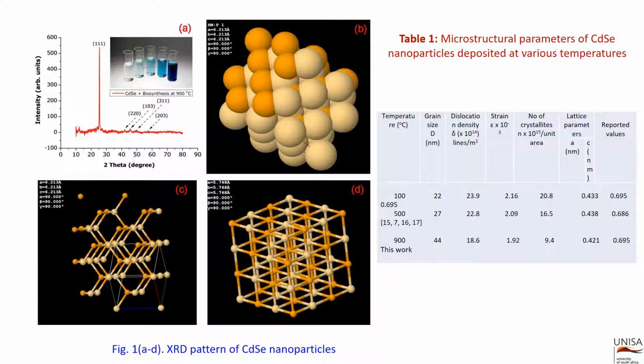In the present study, CdSe nanoparticles show a reduction in the c-axis, which indicates that the nanocrystals are experiencing compressive force in the a direction. The hydrothermally grown CdSe nanoparticles show a larger a value compared to the standard value, which indicates tensile strain along the c-axis. Furthermore, due to the presence of lattice strain with reduced grain size, the nanograin particles are found to have different crystalline structures when compared to polycrystalline or single crystalline counterparts in thin film or powder samples. This is mainly attributed to the reduced number of atoms in the nanoparticles, which reduces the extra free energy associated with surface morphology.